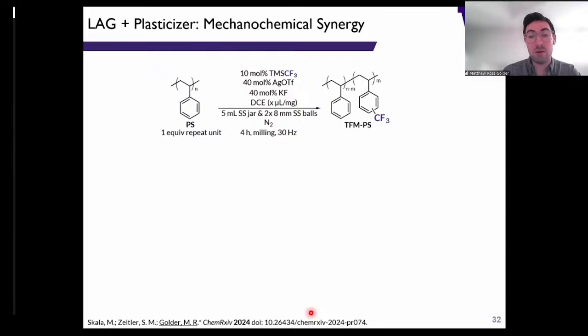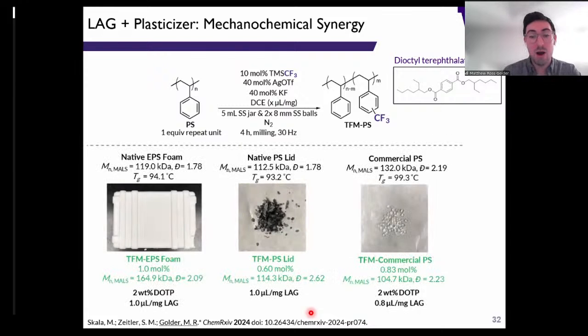So what we settled on was a synergy between liquid assisted grinding and the addition of exogenous plasticizers. We thought that this could have been why the coffee cup lid worked so well in the first place. Perhaps it was inherently more plasticized in the native form. So we went through and we doped in a common plasticizer, this dioctyl terephthalate, to our native waste. We saw a marked increase in both mole percent functionalization as well as control over molar mass.